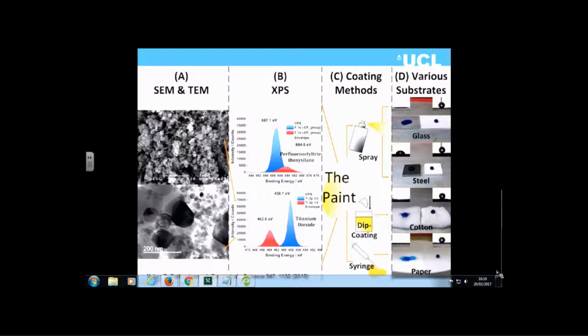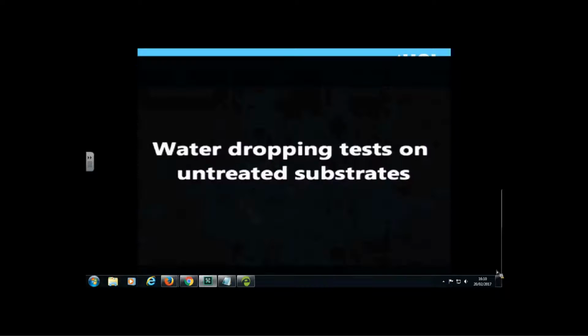This shows TEM and SEM images of our surfaces with the rough microstructure. And over here you can see what happens when you put water droplets onto those surfaces for glass, steel, cotton and paper. I will show, hopefully if I get it to work, some videos which relate to that. But if you have a superhydrophobic surface...